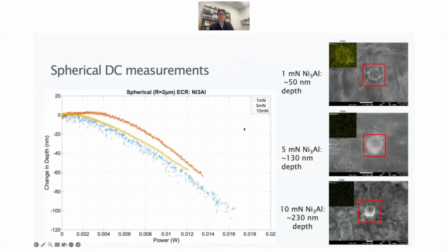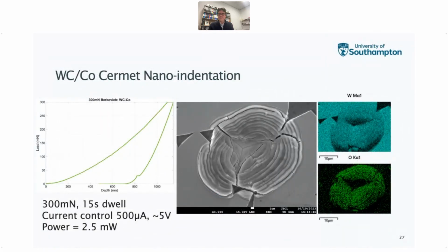And then if we go to the scanning electron microscope again to try and understand why this is, you can see from the deeper indents, it has clearly penetrated, so we've got 230 nanometers for the 10 millinewton load controlled experiment and about 130 for the 5 millinewton. And we have some of the slip planes activating there, as you can see. But for the low contact load, where we're only going about 50 nanometers, you can see we've actually induced a bit of thermal oxidation on the surface there, as you can see from the EDX map here. And so then the power is being dissipated to oxidize the surface, which is not really what we want at all. And if you go to a higher resistivity material, like a ceramic, for example, this is compounded.